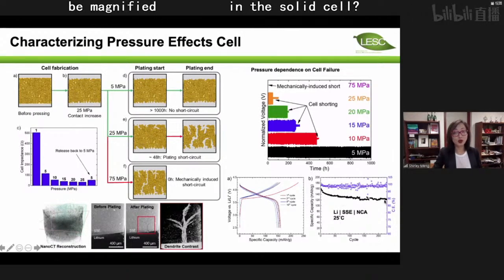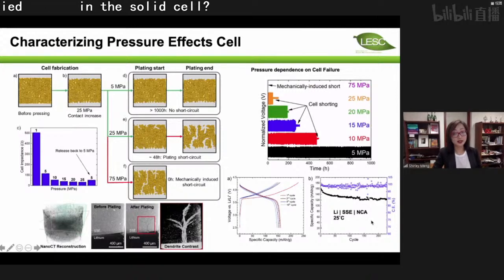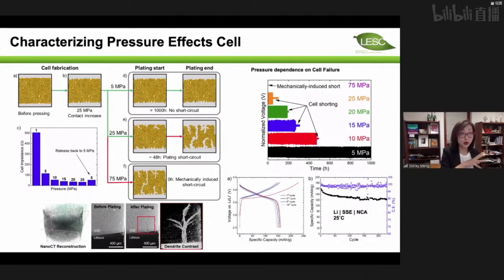Even though here, in this publication, I can show you quite stable cycling, the point here is to prove stability. But for the performance, at this rate, I'm moving the lithium ions 10 times slower than in the liquid case, and that's how slowly I move. This whole experiment takes 3 months to complete, right? So the optimal mechanical setup for the solid-state battery is still a largely unresolved issue.